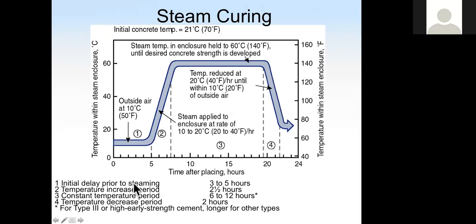Let's look at steam curing. For steam curing, we put the concrete into a special steam curing chamber. Inside the chamber, we can control the temperature. Here shows the temperature inside the steam curing. When we put the concrete inside the curing chamber, the temperature is not suddenly increased to a certain level, like 60 degrees, because if the temperature is increased too suddenly, the concrete may crack or the chemical reaction may change. So we need to slowly increase the curing temperature, like in this second stage. That stage takes about 2 to 3 hours.